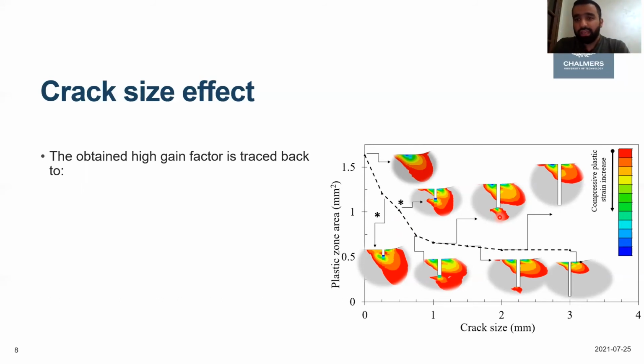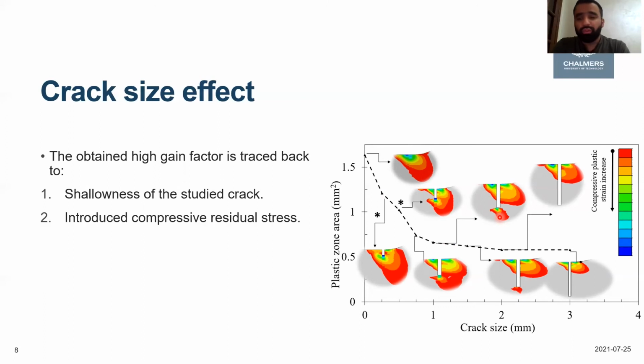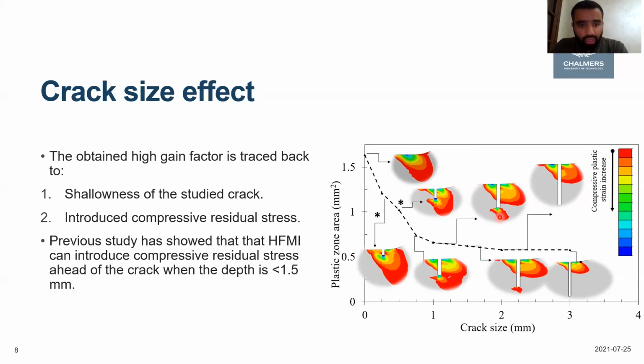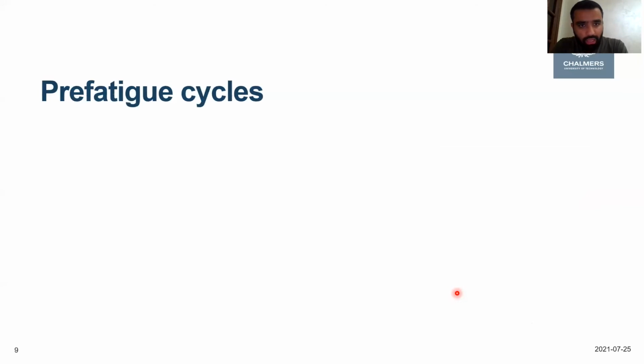And here we can say that it's related to 2 reasons. First, the studied fatigue cracks are shallow, almost all of them less than 2.25 or 2 millimeters. Also, the introduced compressive residual stresses arrest the crack propagation for this kind of crack. In the study, when the crack size is less than 1.5 millimeters, we can get good compressive residual stress to arrest the crack and cause it not to propagate anymore.